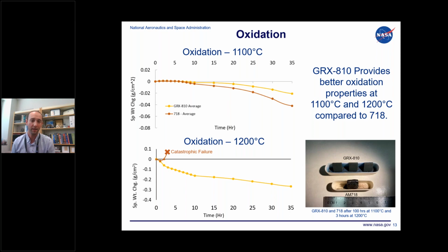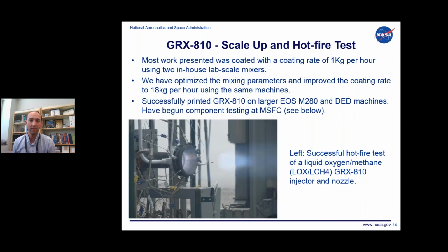718 failed after 3 one-hour thermal cycles at 1200C, basically crumbling into a pile of oxides, whereas GRX-810, though losing oxide, maintains its structure and strength, and we were able to extend the test out to 100 hours on that one. We've actually recently been performing hot fire tests on GRX-810 injectors and nozzles at the Marshall Space Flight Center, and we'll hopefully have those results published soon. So far the tests have been very successful.